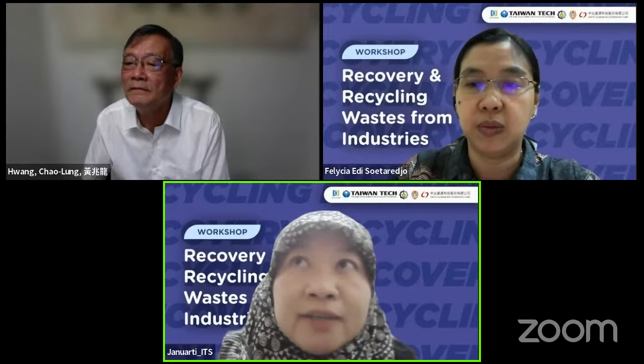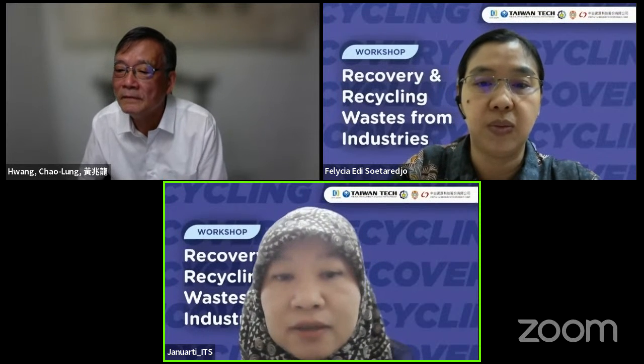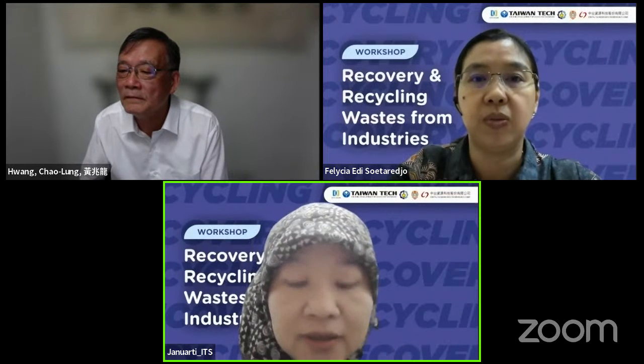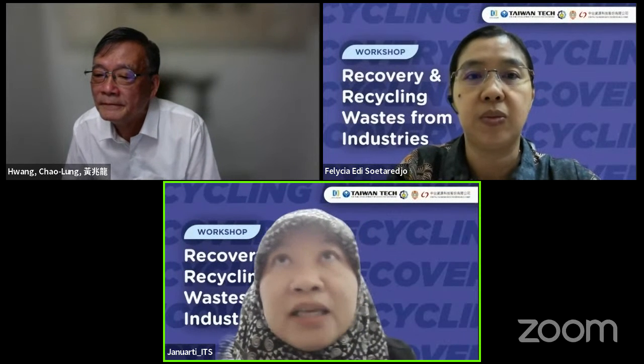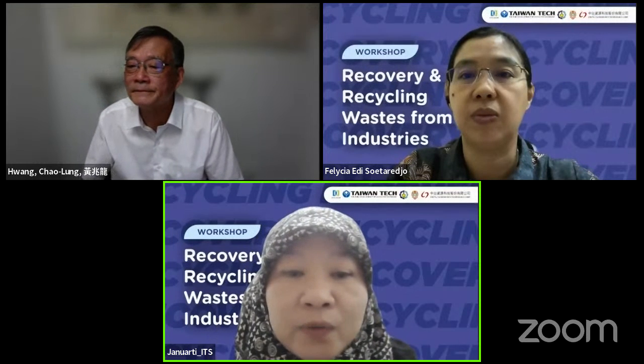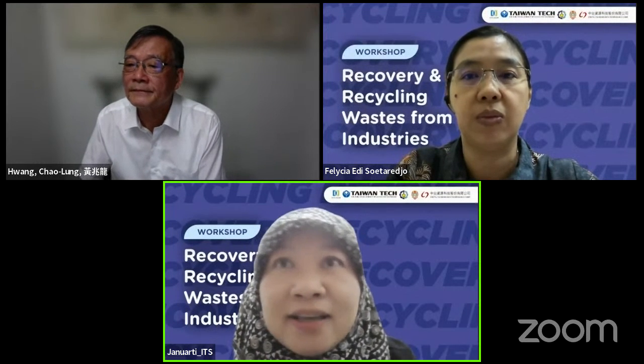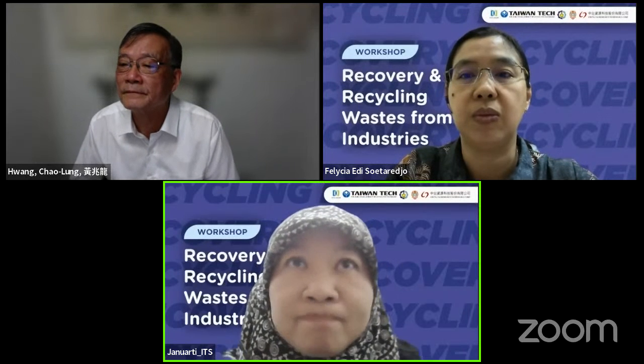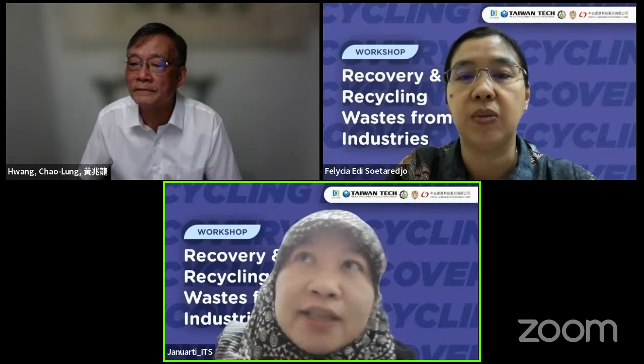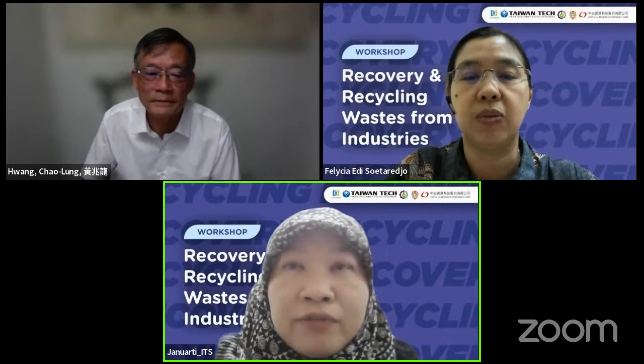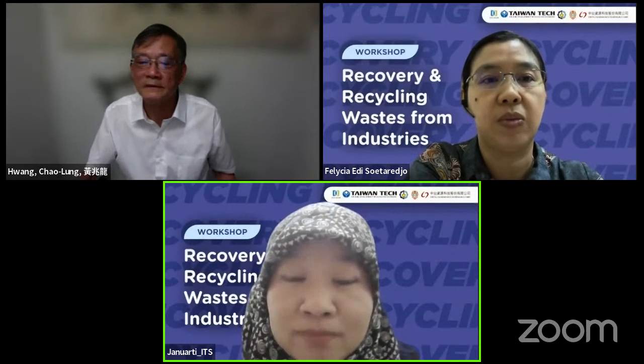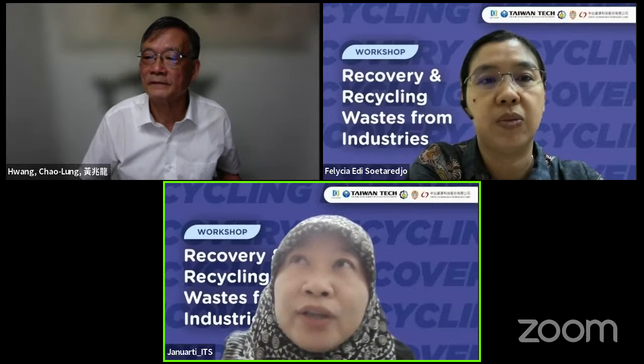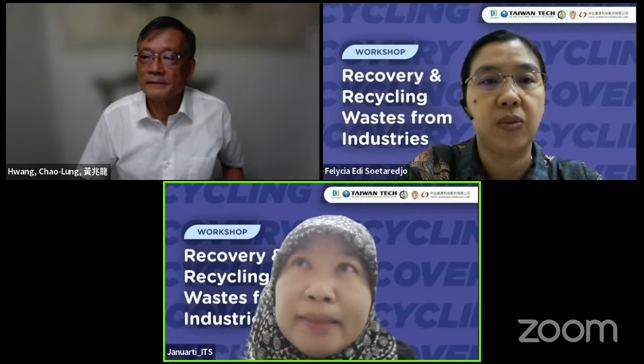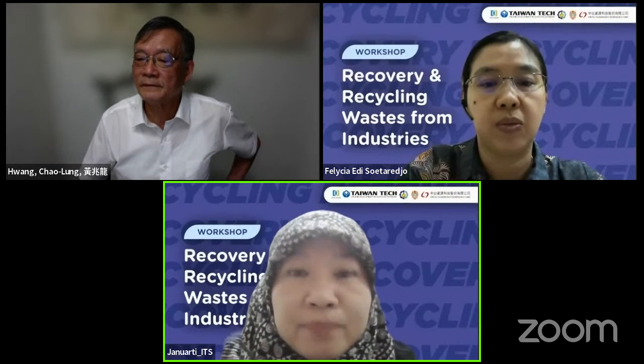But here, by doing the solidifications, for example, we mix fly ash or bottom ash with cement, and also mix the coal ash with the alkali to make it solidify. During my experience in Indonesia or in Japan also, I've never seen any leaching of very dangerous material, for example, like chrome, or we're also worried about maybe zinc or lead or even boron.